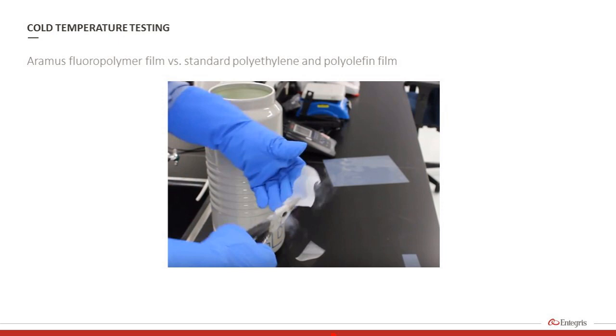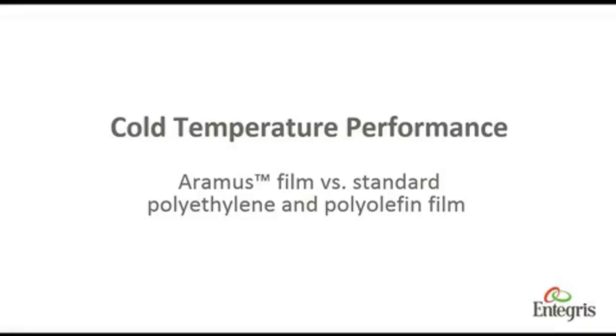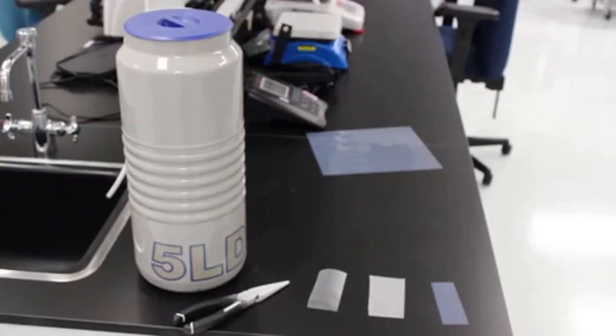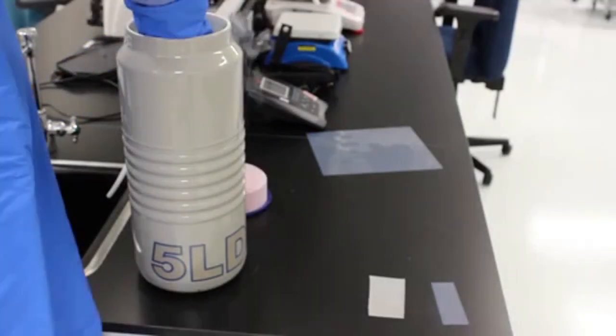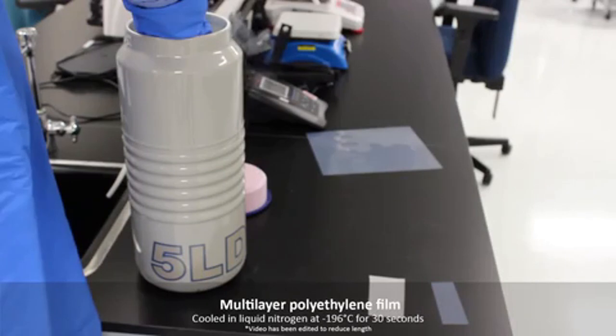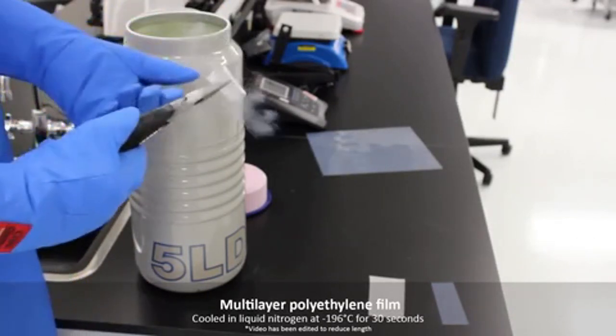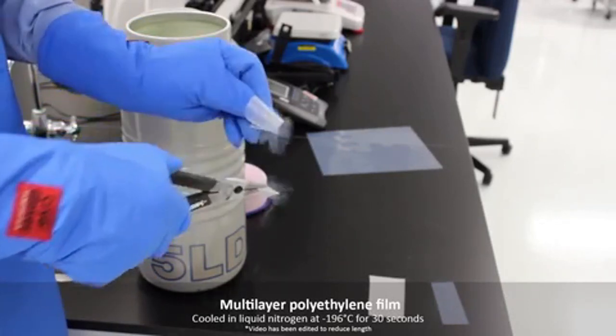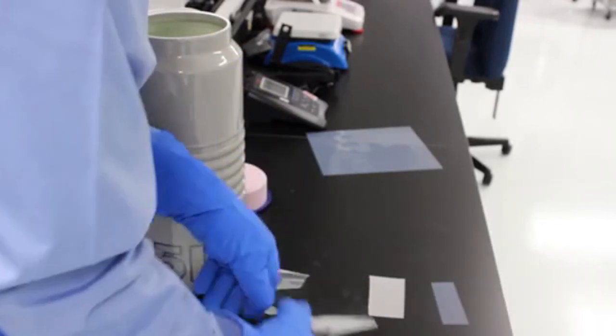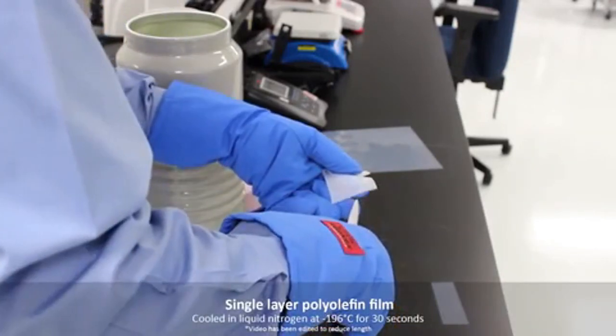Taking the cold temperature testing to extremes, I will now show a video showing how various films withstand exposure to liquid nitrogen at -196. So what you're going to see here is a dewar of liquid nitrogen and 3 different film strips that are being tested. This is a multi-layer polyethylene film that was immersed in liquid nitrogen and removed. And you can see how brittle it becomes after that exposure to liquid nitrogen.